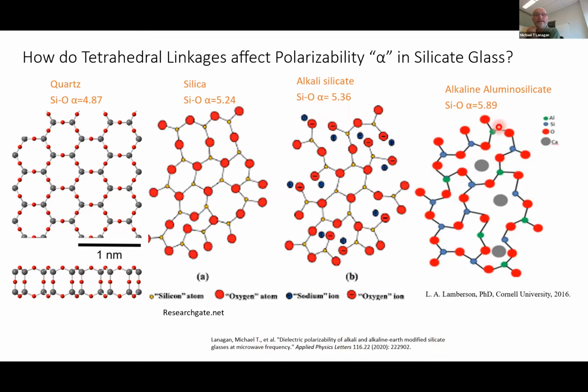And then as we add even more modifier, in this case calcium, the polarizability goes up even further. And then we see that we're breaking up the structure even further. So there are some really good correlations between the fundamental ionic performance of a structure and the polarizability and eventually the loss.